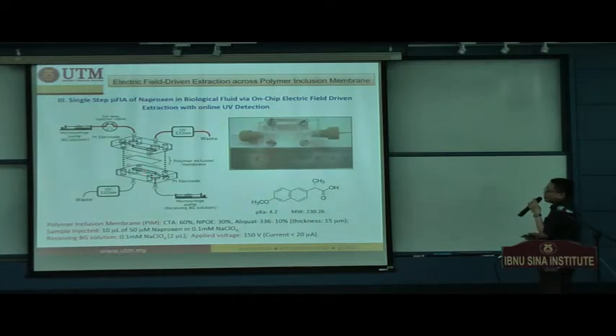And then after the extraction, the microsyringe pump for the receiving solution is turned on to purge all the tiny amounts of enriched analytes through the UV detector for direct quantification. The membrane that we use is the optimized condition here. The membrane is only 15 microns.